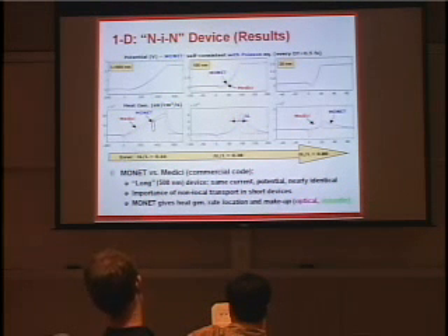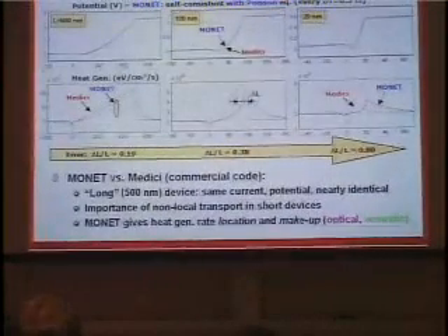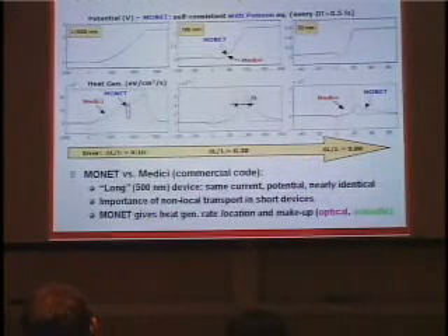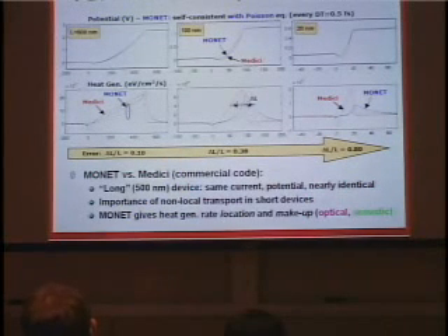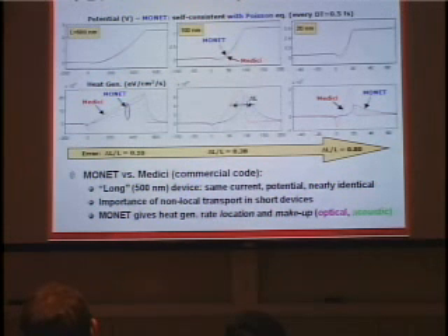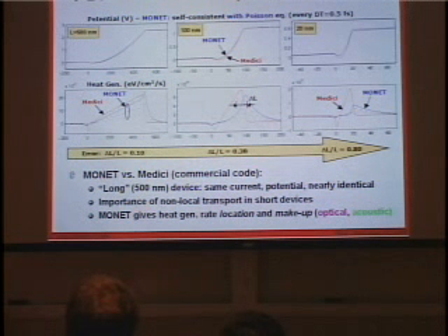We're also seeing that the heat generation rates, which I'm plotting here on this new set of plots, in the 500 nanometer device are quite similar. There's only about 10% error between the location and the peak of these heat generation rates, computed from J.E and computed from the sum of phonons, which I'm doing in this code. However, as we go to the 100 nanometer device, and especially to the 20 nanometer device, we see that the result in the heat generation rate is quite different in Monte Carlo compared to the diffusion code. And first of all, the first thing that we're seeing is that the peak is pushed into the drain.